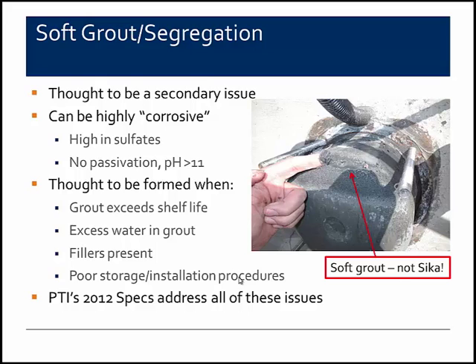There is a suspicion that the fillers, the calcium carbonates that are used in lieu of the really fine sand aggregates, may help produce this soft grout through some type of filtering or clumping as the grout is pumped through the tendons. And then there's also the assumption that poor storage or installation procedures can also result in soft grout formation. So the 2012 PTI specifications do try to address all of these, and it is a much better specification for grouting procedures and practices. And so we think going forward that largely the soft grout issue has been addressed and corrected, but there is a period of time where soft grout was produced.